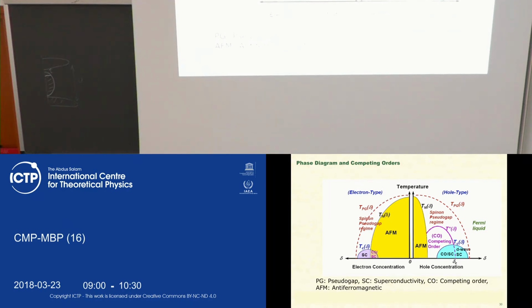Well, I should also mention that there are families of copper oxide superconductors where the carriers are electrons. These are mostly cerium-based copper oxides, but you see that this phase diagram is a kind of caricature on the right side. Namely, the antiferromagnetic phase is much bigger compared to the hole-doped copper oxide, but the superconducting dome is smaller, and there is also room for coexistence between superconductivity and antiferromagnetic states. CO means competing order. Here, just to make the story even more complicated, there is room for a spin glass state, which people observe.